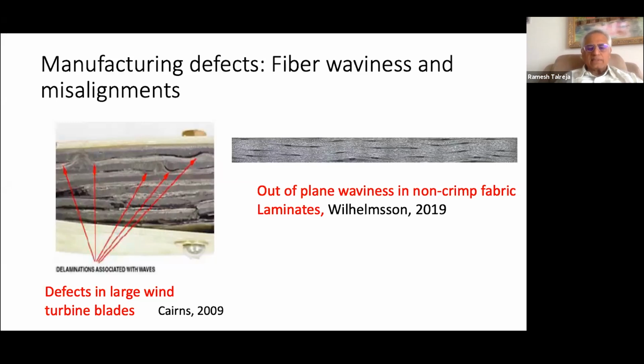Here's again from Sandia report, the section of a wind turbine blade where you can see that thick layers that were stacked on top of each other on curing shrunk and caused a disbond between the layers and therefore delamination under service conditions. Here you see something that has been done in a laboratory environment, but following manufacturing process as it is sort of done in practice. And here are non-crimp fabric layers stacked on top of each other. And after curing, once again, you see the waviness and probably some delamination as well. So I'll come to this particular example a bit later.